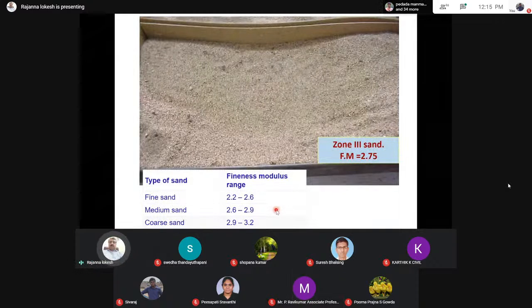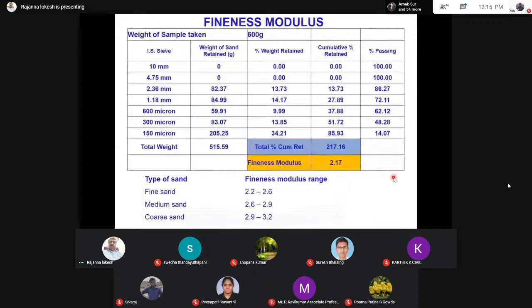You can see the variation in the grading of the sand, and also you can see the variation in the value of fineness modulus. So in all possibility, we are going to have a fineness modulus of 2.2 to 2.6 for fine sand, 2.6 to 2.9 for medium sand, and 2.9 to 3.2 for coarse sand. And once the sand is procured, we have to check the fineness modulus. It is a simple test.